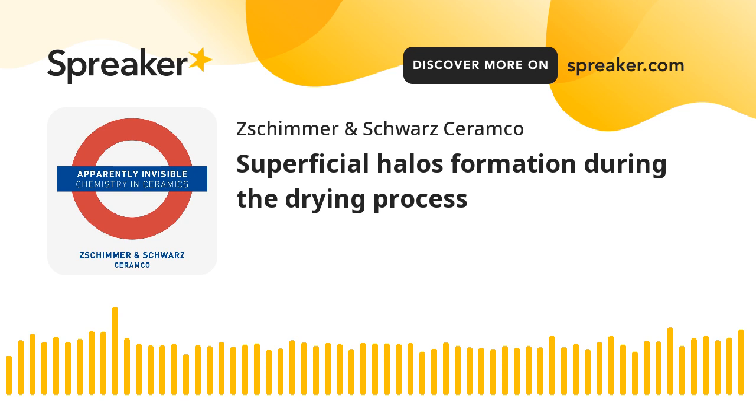In other words, we could also say that the lack of residual humidity would be, at this stage of the process of course, a serious problem, because the raw materials that form the ceramic body wouldn't be correctly pressed. That said, if the presence of residual humidity allows you, on one side, to give shape to the ceramic support, on the other side, it's an issue because it negatively affects the tile's mechanical features that are necessary for the following application. What does it mean? It means that the water makes the raw tile more fragile, and so it can be more easily attacked by the stress that may arise along the conveyor belts of the production line.